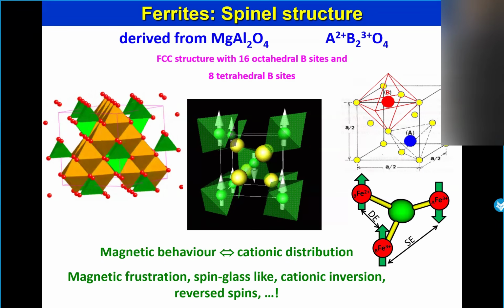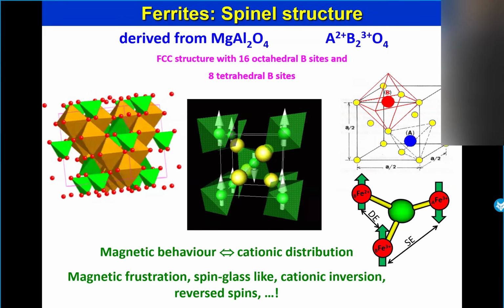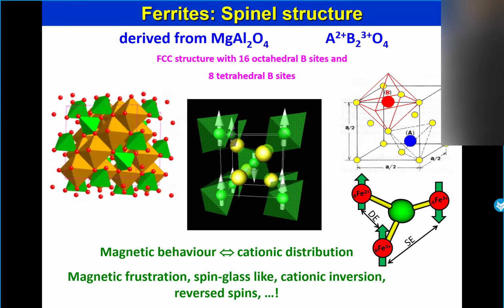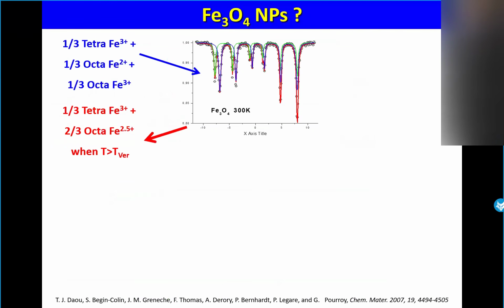As I mentioned before, in the case of micro, as well as in the case of nano, ferrite. Of course, in the case of nano, you have to add the contribution of surface. So now the big problem of magnetite nanoparticles, because everyone for 20 years was doing nanomagnetite, but finally, is it nanomagnetite? The typical spectrum of magnetite is like this. You have two main components at room temperature, that means above the Verwey transition, which is 119 Kelvin.